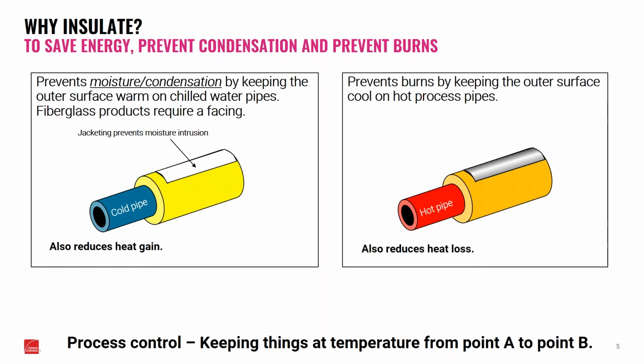So on the one hand, if you look at the image on the left, if we're insulating a cold pipe, we're just trying to keep the contents of that pipe cold as we transport it from point A to point B. So we insulate that to help keep heat from getting into that system. Also, because that's a cold pipe, moisture wants to condense on it. So the only barrier between that cold pipe and the moisture in the ambient air is either the insulation itself, like in the case of foam glass, which is pretty impermeable, or maybe a fibrous insulation like fiberglass with a jacketing over the top of it that helps prevent moisture from going from the ambient condition and condensing on that cold pipe.